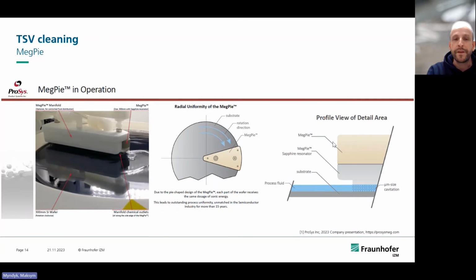Another technology approach is the so-called MegPie. For MegPie, we contacted an external company, and this process is patented. Very briefly, the idea is completely different in comparison to SSEC. We apply, using this triangle, megasonic energy onto the wafer surface, and the megasonic energy is much higher in comparison to SSEC. The energy is transferred through the fluid layer into the wafer surface. In both cases, SSEC, our existing tool, or MegPie technology, we will use the same chemistry from Technic France, D-BOS 390.